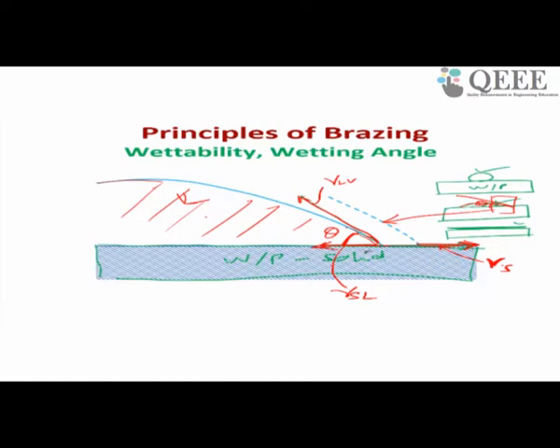So for making equilibrium, what should I do? Gamma S should be equal to the surface energy of liquid-vapor times cos theta plus this one, gamma SL. So to maintain equilibrium, the surface free energy of the solid should be equivalent to the summation of this product plus this one: gamma LV cos theta plus the surface energy of solid-liquid.